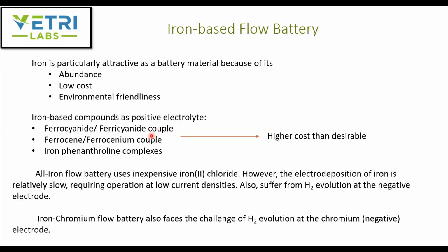And there are some iron flow batteries that use inexpensive iron 2 chloride solution. For example, you have the all-iron battery, where you have iron metal as an anode, and on the other side a carbon felt as a cathode. Or you have an iron chromium flow battery. Even though they use an inexpensive iron 2 chloride, they face a challenge from the hydrogen evolution at the negative electrode, where it's iron in the case of the iron flow battery and chromium in the case of the iron chromium flow battery.